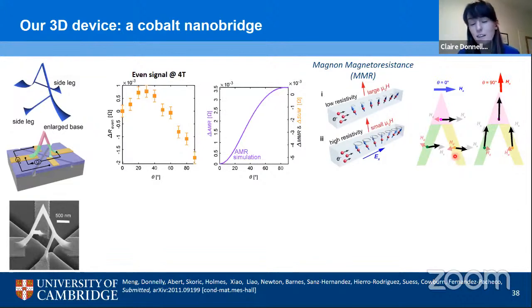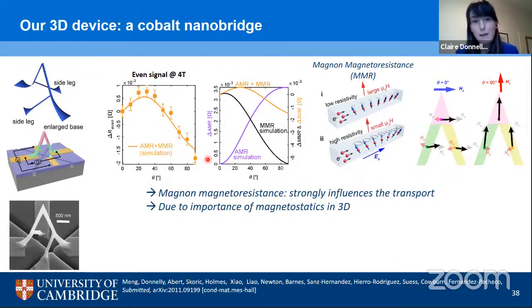that needs to be the total magnetic induction. And indeed, when we incorporate this model into our simulations, we see the opposite angular dependence of the MMR to the AMR, which allows us to reproduce this angular dependence of our 3D structure. Meaning that the takeaway message is that we have this magnon magnetoresistance that in 3D structures can lead to a very strong angular dependence. And this is due again to the influence of magnetostatics in 3D, almost reminiscent of our work with the vortex rings.